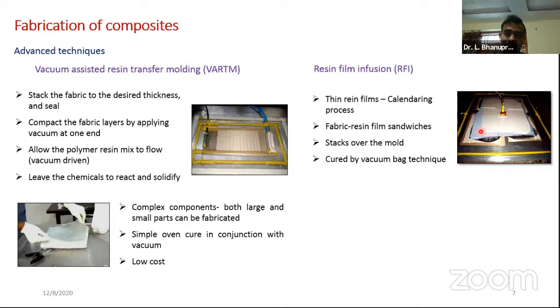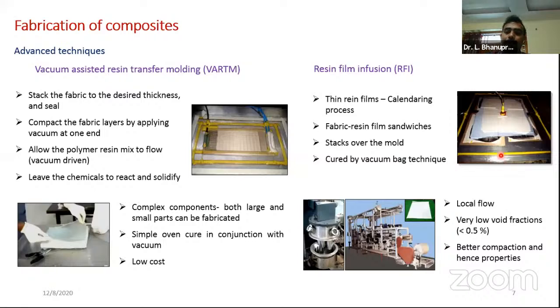We have excellent control on the resin that is present between the fibers. We get very low void fractions, less than 0.5 percent, and greater compaction, so the properties will be very good. This is a calendering equipment, where we can prepare these polymer resin films. These are the two advanced methods using which we can fabricate fiber reinforced composites.